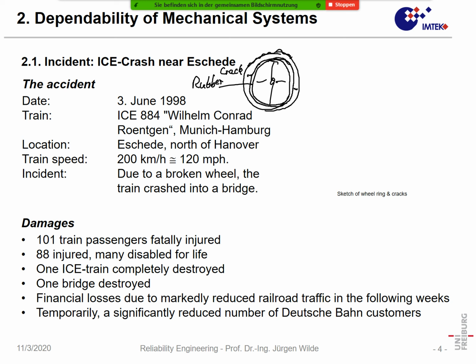Unfortunately, it just broke directly before the train met the bridge. The train was derailed, and the derailed wagons were running into the pillars of the bridge. The bridge collapsed, and it buried the rest of the train, and that was the reason for these many fatalities. As an engineer of material science, I'm extremely sad that this happened, because that was a typical accident which happened before in the 19th century. It was very frequent, let's say up to 1880 or so, and then in Germany very much research was performed in order to clear up this phenomenon of fatigue.